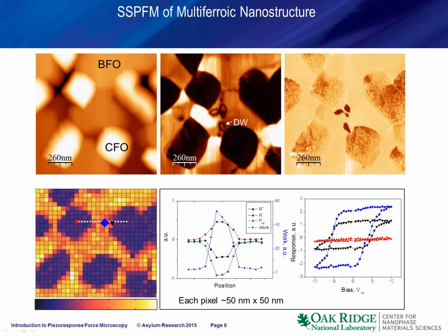Now, what you can see is the SS-PFM map when we take a number of the hysteresis loops and plot the area under the loops as the color map. So you can see that the hysteresis loops are open in bismuth ferrite and hysteresis loops are closed in cobalt ferrite. So not too much surprise here. We can extract the hysteresis loop from different locations on this map, and as you can see, this is exactly the behavior. So in the red triangular dot, the loop is closed, and in the blue dot, the loop is open.